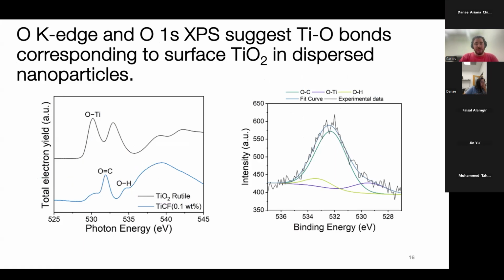Then we did O K-edge XAS, with O1s XPS as well. We see in TiO2 rutile, you can see the Ti-O bonds here. And then in our nanoparticles, we see our carbon-oxygen bonds and our hydroxide bonds, which are generally always there in these carbon supports. But we see a slight appearance of these Ti-O bonds over here, which indicates that we do have some titanium being bonded to oxygen as well, besides nitrogen.